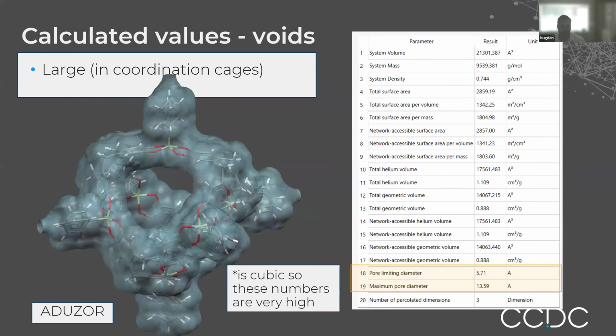There we are. So other things you would do with a void analysis tool is to look at large voids. So for instance, in coordination cages like Adusor. So this is a large volume, medium pore diameter. So after deleting the compound in a cage, we can look at the maximum pore diameter, which is 13.59. That's about the size of a ruthenium complex. But the 5.7 angstrom pore limiting diameter is too small for that complex to get out of the cage. And so you can start making decisions on what material is going to be useful for which application.